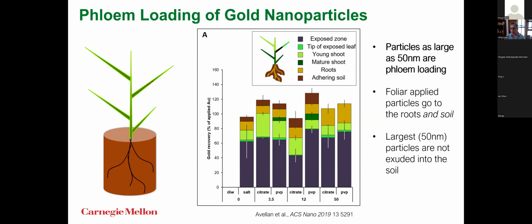All right, so this goes back to that first paper that I showed you where we put the gold nanoparticles on the leaves. And I showed you that they went into the leaves, got stuck in the mesophyll. If we go in and look at where they went in the rest of the plant, this is all color coded. So these gold bars here are the percentage, or the fraction of the material, that goes to the roots. What we found, interestingly, was something like 25% went to the roots.